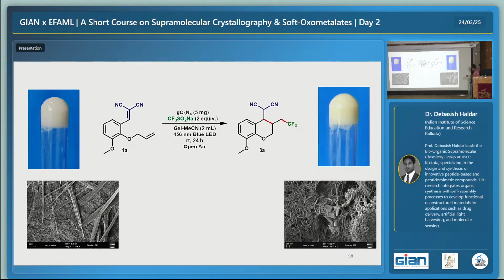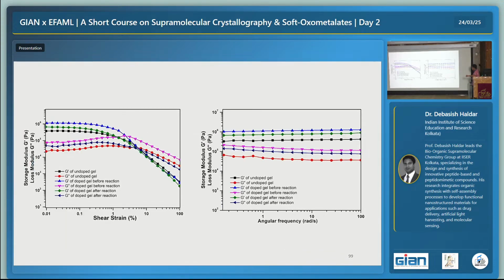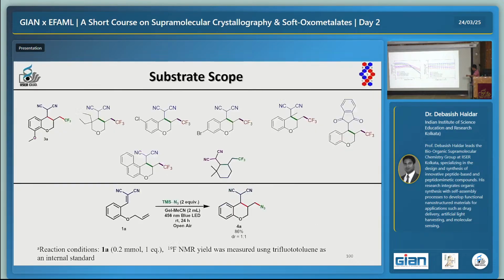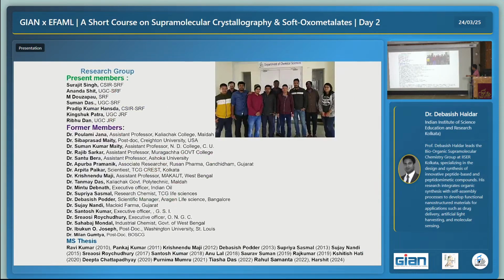And this is the morphology of the gel and the reagents before reaction, this is after reaction, so the morphology of the gel is almost intact. And we have done rheology before gelation, after gelation, before doping, after doping with the reagent, and after irradiation of the light. And this is the substrate scope, so we can do this reaction with many substrates, and they are giving very nice yields.